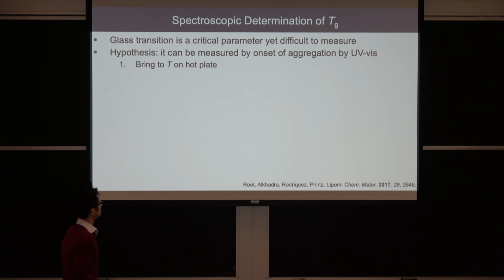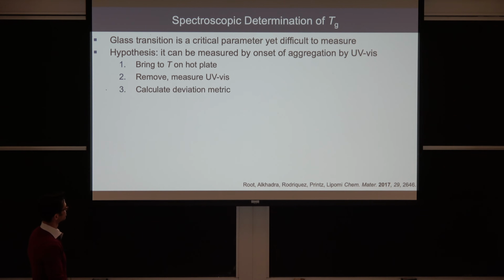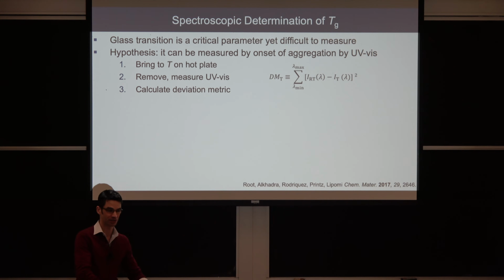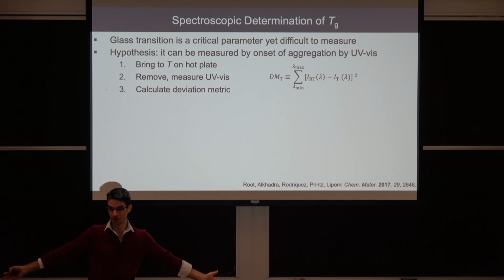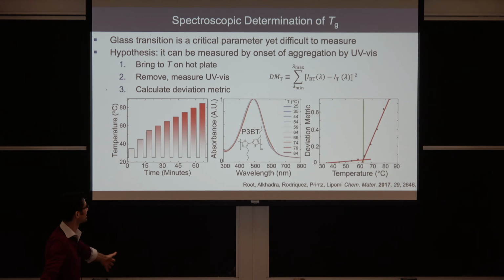So the idea was to use a hot plate, and you bring your sample to a certain temperature on a hot plate and you measure the UV-vis, and you calculate something called the deviation metric. And my student came up with this, which is the sum of the squares of the differences in intensity of absorption from some reference temperature to some temperature of interest. Nobody here knows what I just said. So here's a picture, and I would not have understood it just based on this.